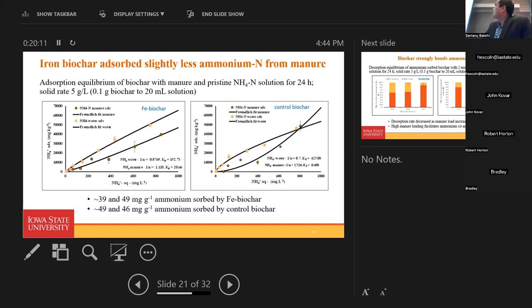Now, into the ammonium nitrogen. Iron biochar absorbs slightly less ammonium nitrogen from manure. This is the absorption equilibrium of biochar with ammonium nitrogen solution for 24 hours, and we tested the iron biochar and control biochar. The rates are quite similar for the iron biochar and control biochar in terms of ammonium, around 39 and 49 for iron biochar and 49 and 46 for control biochar. In both cases, the isotherm follows the Freundlich isotherm, so it's a non-specific physisorption.